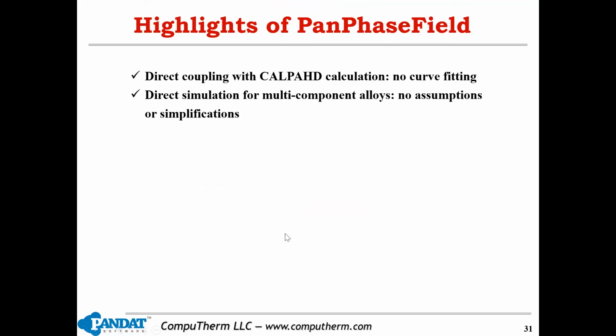So in this module, we directly coupled CALPHAD calculation with phase field modeling. No curve fitting is needed, okay? And we can directly apply it to multi-component alloys. We do not need to make any assumption for binary or pseudo-binary or ternary, okay? And a very key feature of this platform is that we allow users to plug in their own model. So it basically has an open architecture, okay?